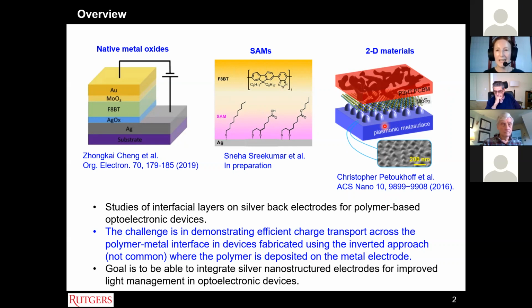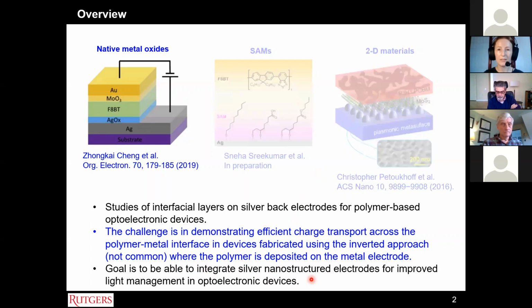If you do it as is conventionally done, where you're depositing the metal as the last step on top of the organic semiconductor, then you can't really control the metal surface geometry or structure. You have to do some imprinting into the polymer, and that creates all sorts of variations in the surface of the silver. So we want to be able to integrate silver nanostructured electrodes to improve light management in optoelectronic devices.